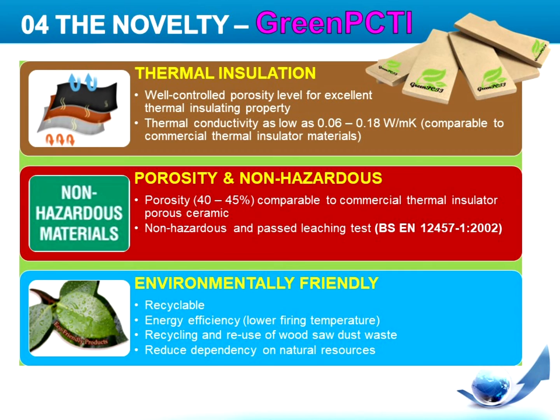Number 2, porosity and non-hazardous. The Green PCTI has porosity level of 40 to 45%, comparable with the commercial ceramic-based thermal insulator. It has passed leaching tests and is non-hazardous despite being made from wood sawdust waste. Last but not least, number 3, the Green PCTI is environmentally friendly. It consumes lower embodied energy during production since lower firing temperature is employed, and it is recyclable.